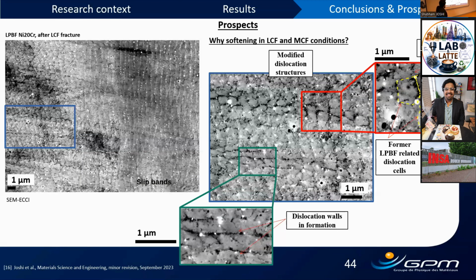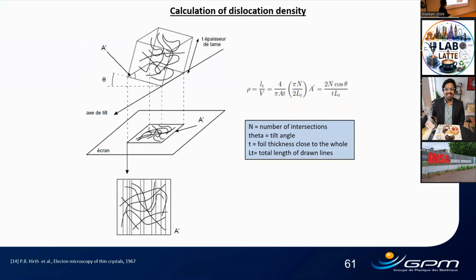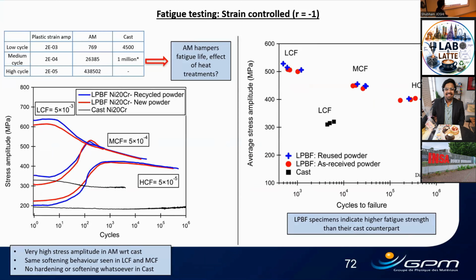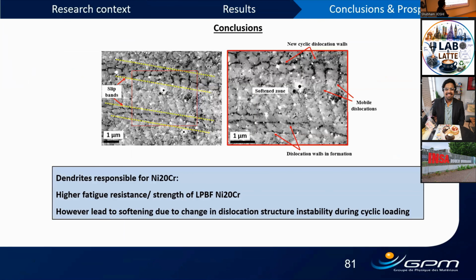And if you look at the magnified new dislocation walls or dislocation cells, what we see here is that it's thicker, but preferentially here we do not see any dislocations at all. The reason we think this is thicker and bigger makes sense because we saw a lot of mobile dislocations with the same shape as these thick walls. So it seems like these mobile dislocations are moving internally to reach one part of the wall from other wall parts. From one side to the other one? Yeah, they are building up there? Seems like that, yeah. So we also did some EM at the softening zone.